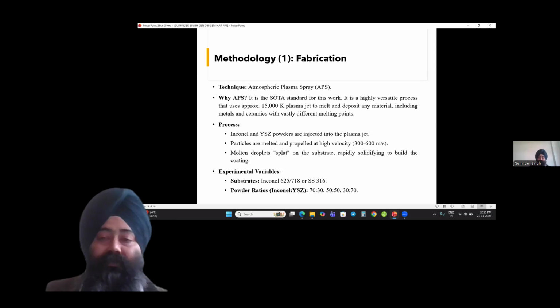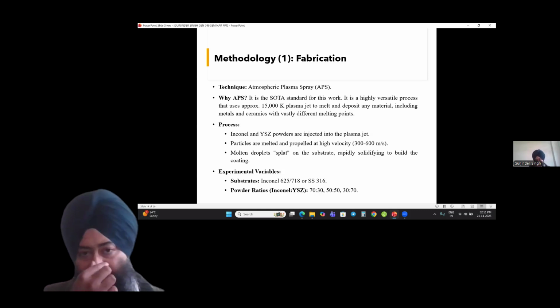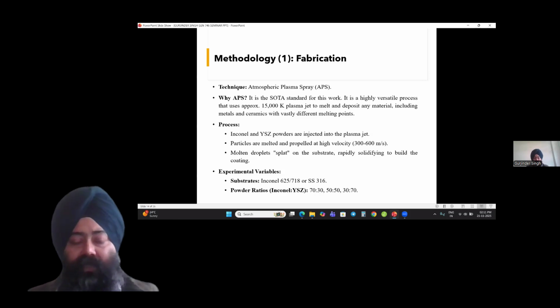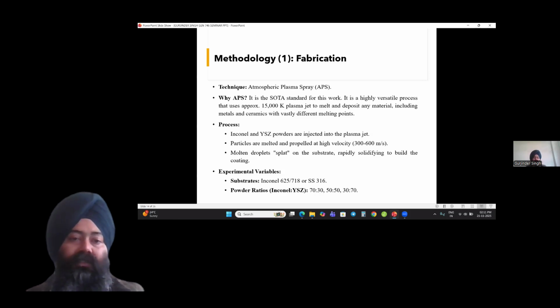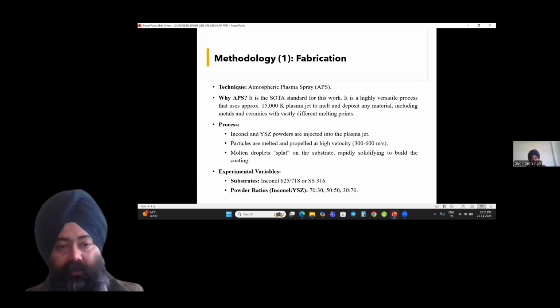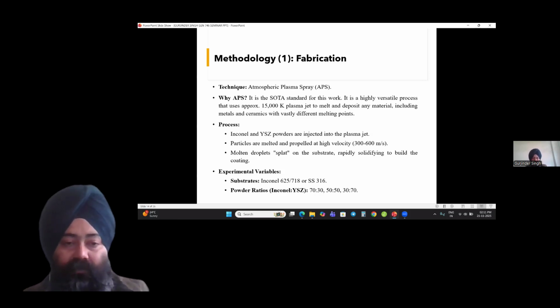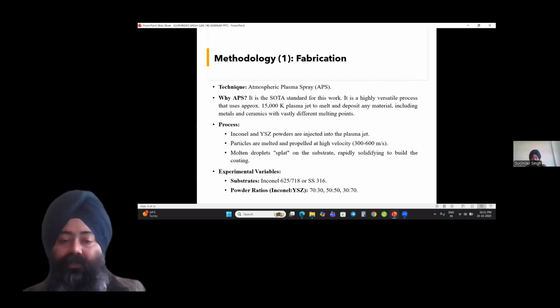Now, what are the methodologies? That is fabrication. The first technique we are planning to use is atmospheric plasma spray, which is the state-of-the-art standard for this work, because in this process we use an approximately 15,000 Kelvin plasma jet to melt and deposit any material, including metal and ceramic, with vastly different melting points. So what is the process? First, we mix Inconel and YSZ powder, and then we inject it into the plasma jet. In the plasma jet, the particles melt and are propelled at a high velocity, 300 to 600 meters per second.